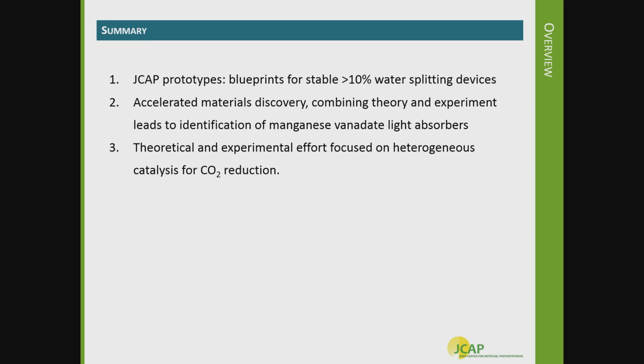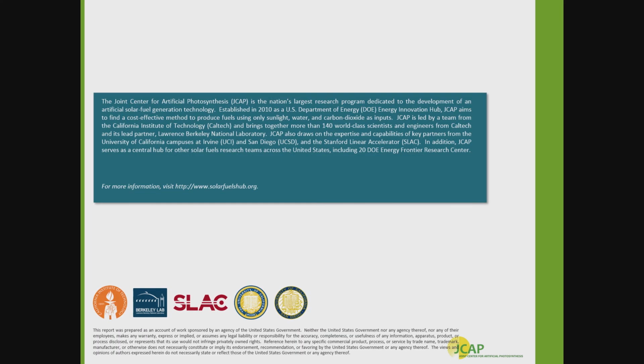Okay, so just what I'll do is now note that over the first phase of JCAP, we've developed, using an integrated approach, prototypes which give blueprints for stable, greater than 10% water splitting devices. And a hallmark of JCAP has been an accelerated materials discovery effort combining both theory and experiment. I showed you an example which led to the rapid identification of manganese vanadate as a potentially stable and electrochemically stable, high photocurrent light absorber material. And I described briefly some of the work that's underway on heterogeneous catalysis for CO2 reduction. So thanks very much, and we'll be happy to field any questions.